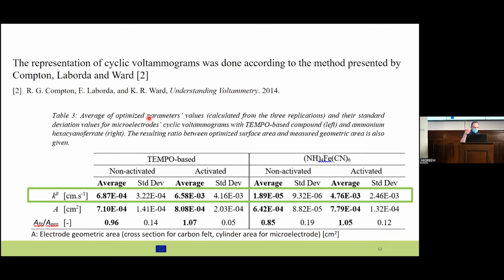And so we do the analysis, and now we have this kinetic analysis. The value we get is slightly different. We think that this model is more accurate, but the kinetic value we get compared to the macro scale, with the macro fiber scale, is a little bit different. So we were wondering, is it accurate? We get a number, is it a good number or not?